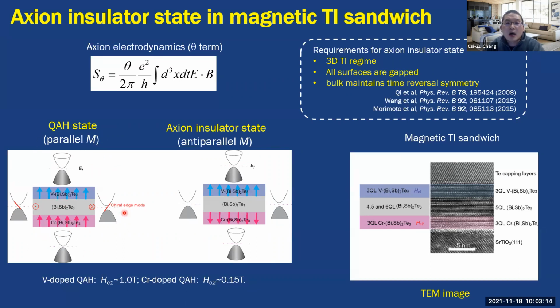This is just the quantum anomalous Hall state. At some magnetic field regime, maybe the chromium doped TI points down and the vanadium doped TI points up. So in this situation, the top and bottom surfaces are gapped, and on the side surface there is no chiral edge state, and because of the quantum confinement effect, there is also a gap opening. All the surfaces are gapped, and the bulk maintains the time reversal symmetry. This just satisfies all three conditions of the axion insulator state.